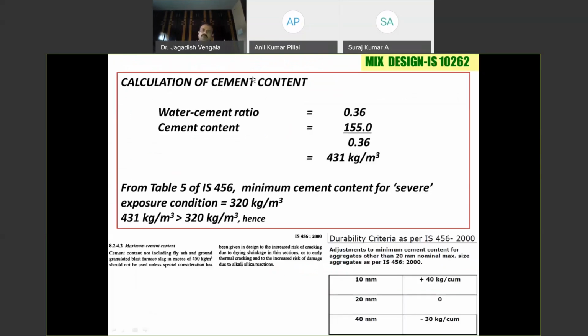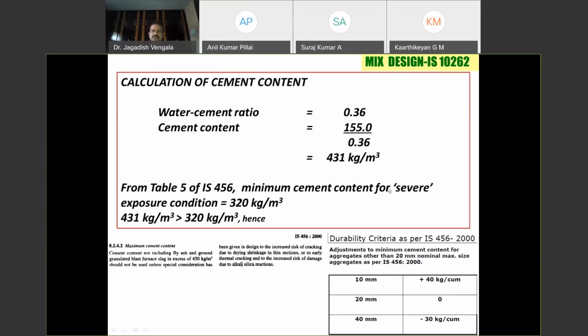Once you have the water content and the water cement ratio, water by cement equal to 0.36, you get the cement content. So here the cement content is 431 kg. For the severe condition, for the durability requirement, when you see the table, the minimum cement content is 320 kg. So 431 is much higher than 320 kg, hence the durability consideration is satisfied.